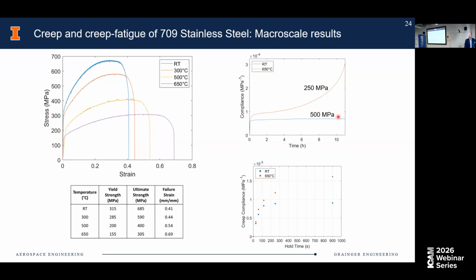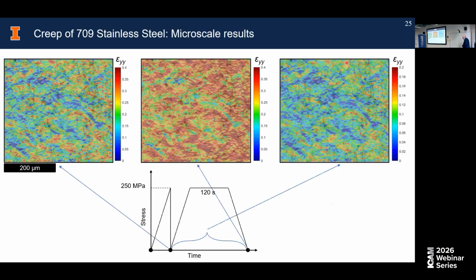This blue line here would be at room temperature. This red line is at elevated temperature, at 650 C, which was the operating temperature. And the 250 versus 500 MPa are the same fraction of yield stress at that temperature, if you're wondering where those numbers came from. So that is what we would expect from a macro scale, but what about micro scale? Do we get the same type of strain accumulation in creep, and potentially at the same locations as we would in plasticity?